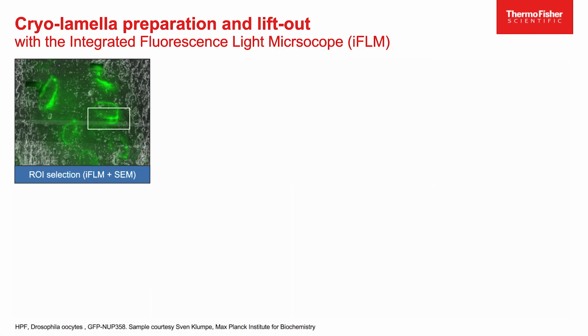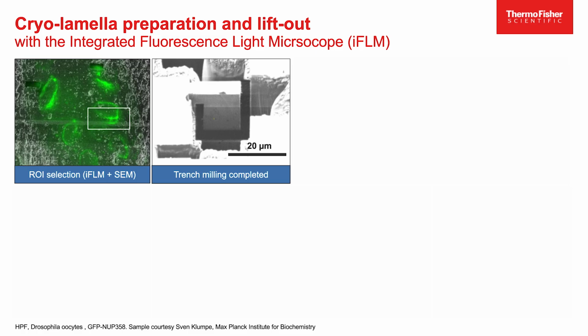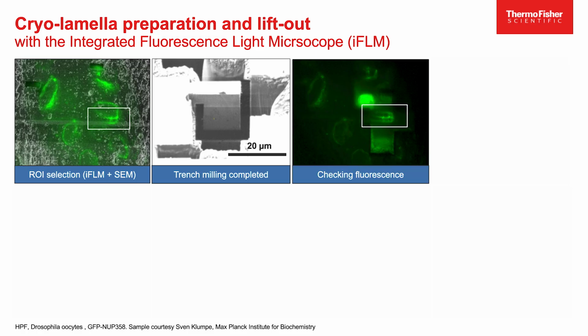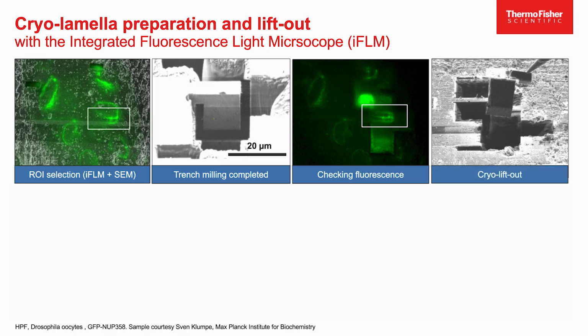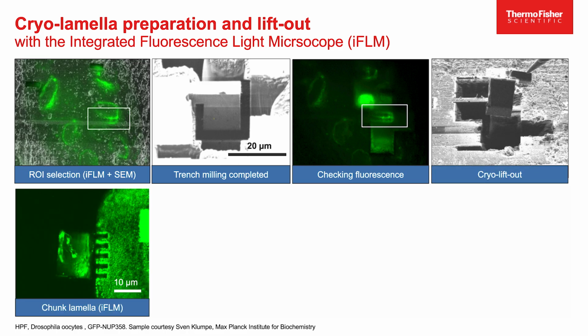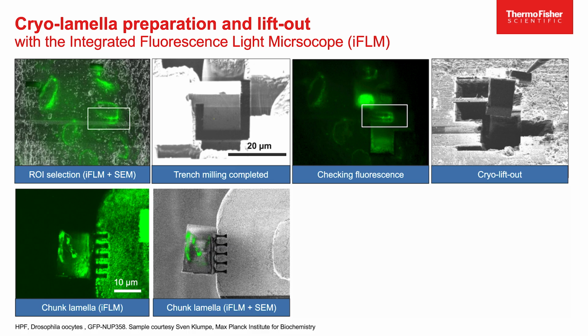What I particularly find important is that you can really navigate and target your region of interest in such a way that you can have step-by-step confirmation of your region of interest while you're preparing the lamella. This means that by the end, when the lamella is already finished, you can still confirm that your signal or your feature of interest is still within the lamella.